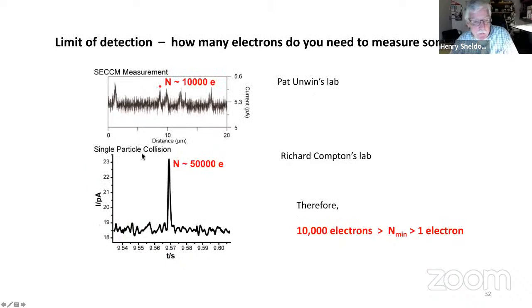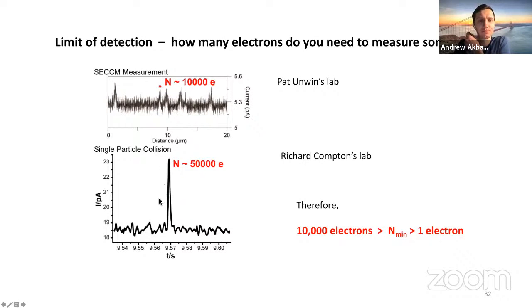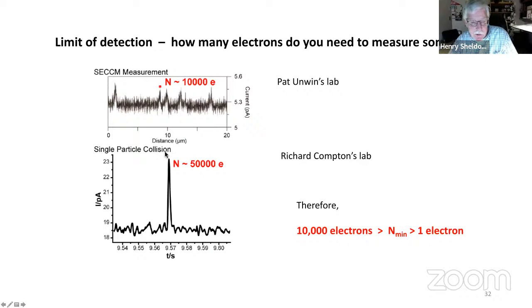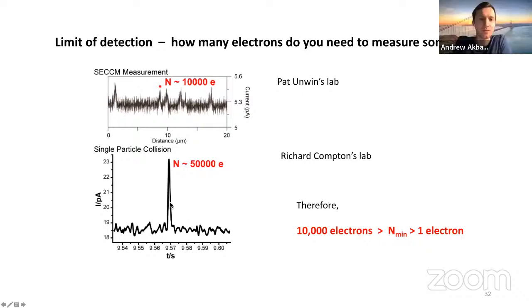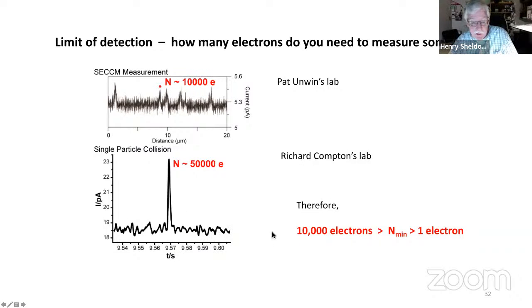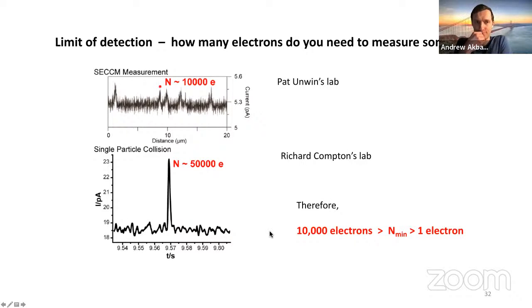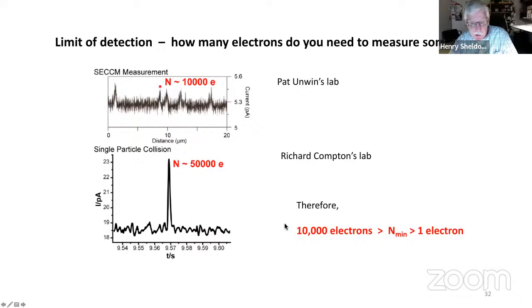This is a silver particle, I forgot how big, 10 nanometers, roughly. And it collides with the surface. The electrode potential is set so it oxidizes the silver. And you see one peak here, you oxidize all the silver. The width here is on the order of a few milliseconds or so. And if you wait long enough, you'll see another peak, maybe 5 seconds later. It depends on the concentration how these peaks are spread out.